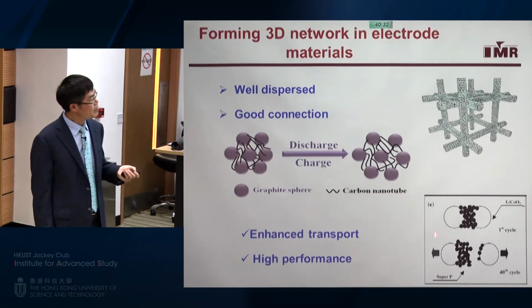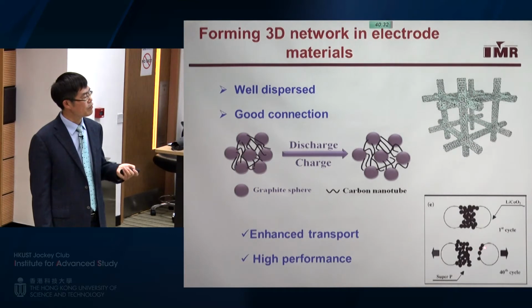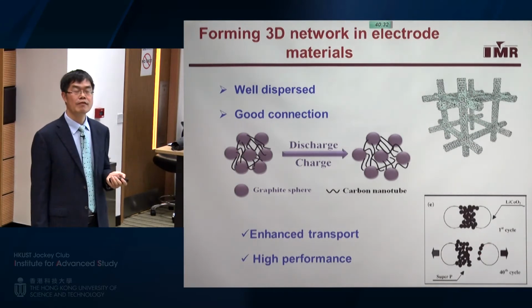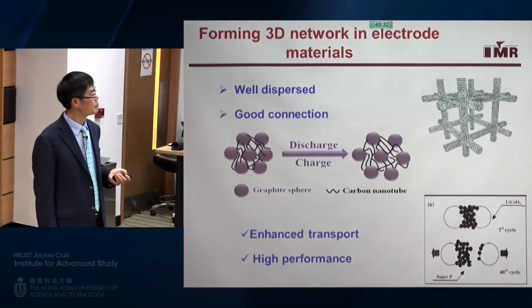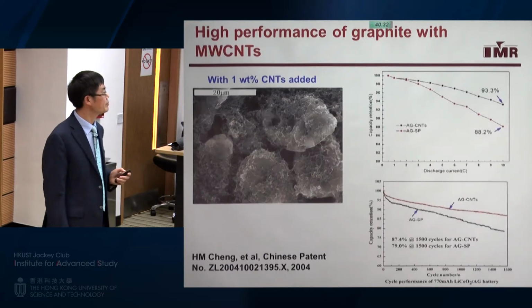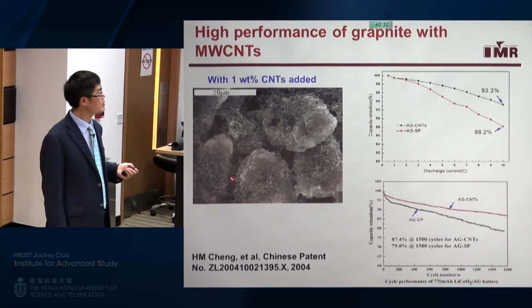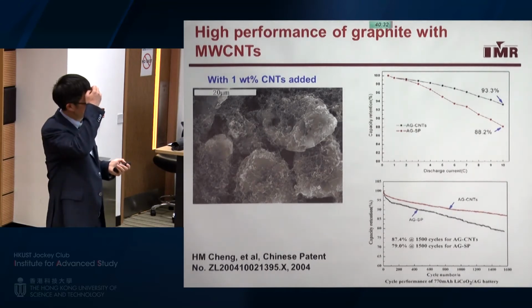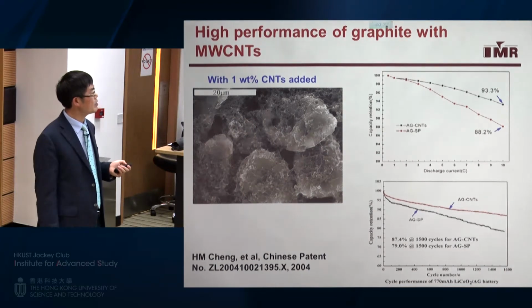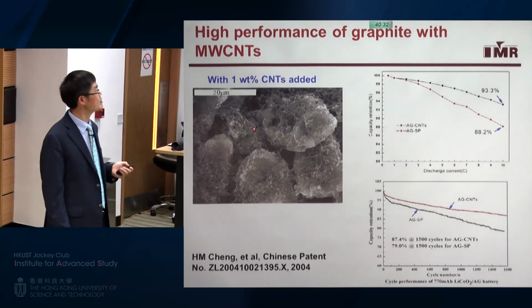However, if we use traditional conductive carbon black like this, during charge and discharge the active electrode materials will detach from each other, giving a very poor cyclic performance. So by using carbon nanotubes, we can enhance the transport. As I show you here, this is a very early work. We are one of the pioneer groups to first introduce carbon nanotubes into lithium-ion batteries.